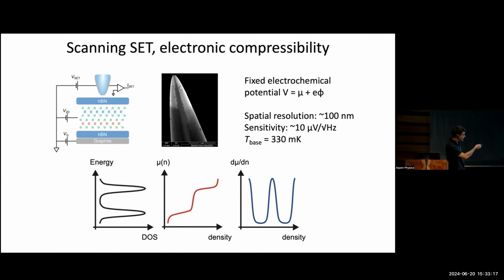And schematically, it looks something like this. If you have two flat bands, peaks in the density of states in your system that you'd like to study, as you're adding electrons one by one, when you're filling this peak in the density of states, the chemical potential doesn't change very rapidly. So you get a plateau in the chemical potential. As you traverse this low density of states, there's a jump in chemical potential. And then as you're filling this next peak in density of states, you get, again, a flat behavior. In practice, we often measure the derivative of this. That is, we apply an AC voltage to the backgate, and then the step in chemical potential turns into a peak in inverse electronic compressibility, d mu dn. That is what we're sensing in our experiment. So any large signal that we see in our experiment corresponds to an energy gap, or more generically, a low density of states.